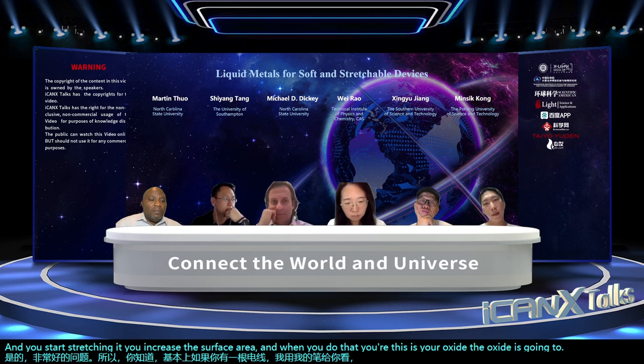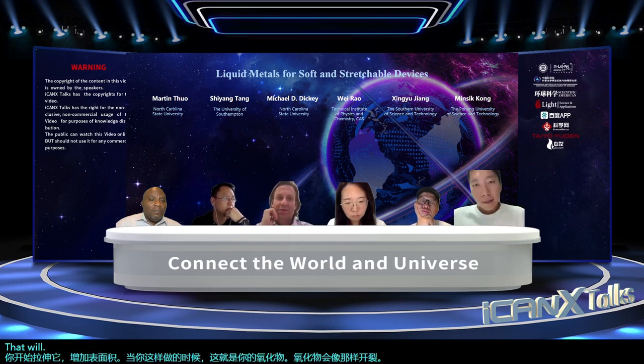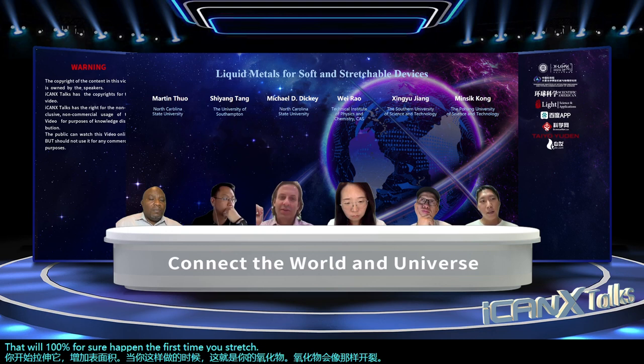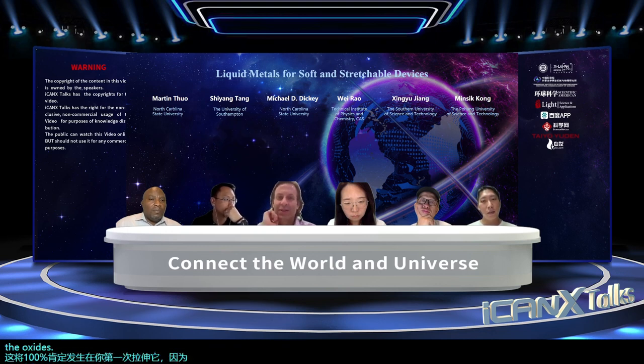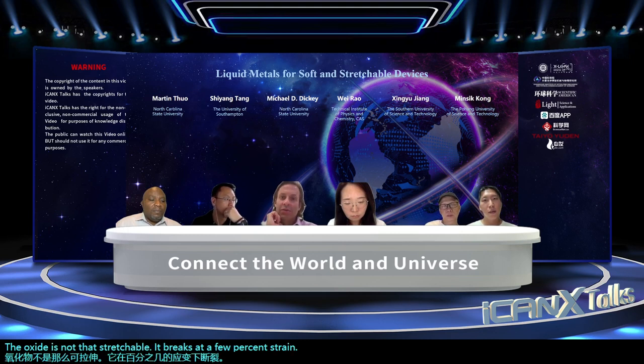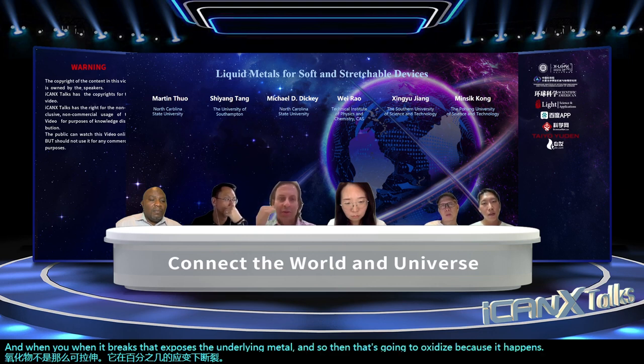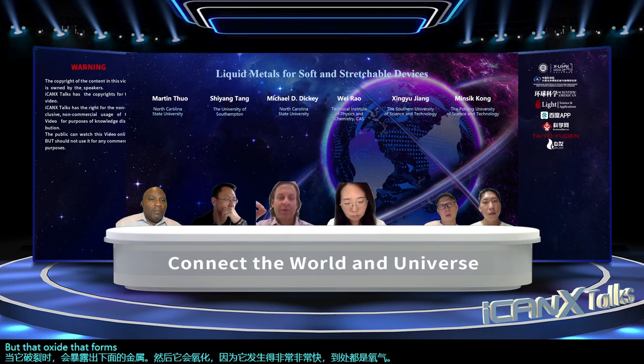And that will 100% for sure happen the first time you stretch it, because the oxide is not that stretchable. It breaks at a few percent strain. And when it breaks, that exposes the underlying metal. And so then that's going to oxidize, because it happens very, very quickly and oxygen's everywhere. But that oxide that forms is very, very thin. It's only a few nanometers thick.